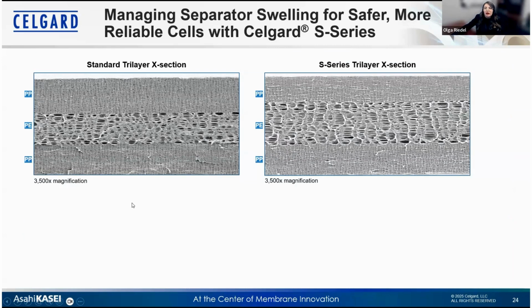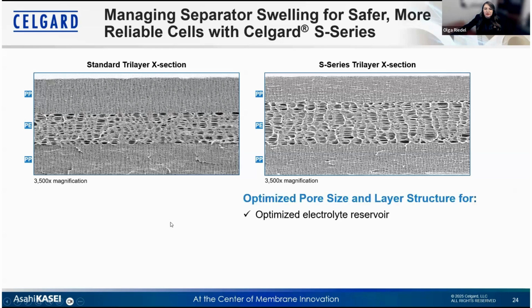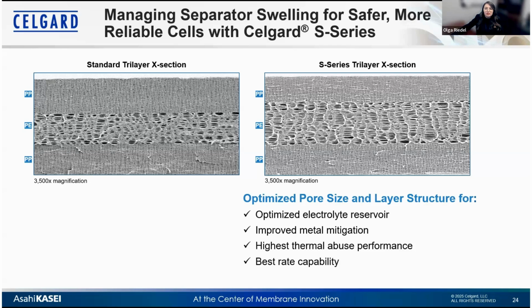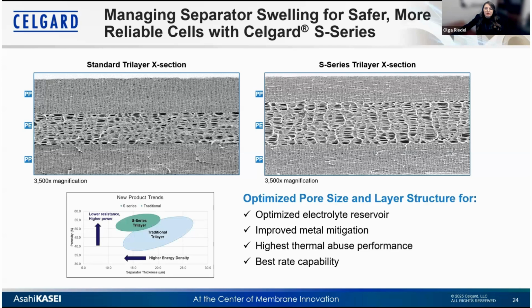At Celgard, we developed our so-called S-series trilayer that differentiates from the traditional trilayer by an improved layer structure and also improved pore size. This helps to create an optimized electrolyte reservoir in the middle PE layer, but also helps with thermal abuse performance due to faster shutdown of our optimized layer structure. Additionally, the low Gurley and the higher porosity help to improve the power performance and therefore enable the best rate capabilities among all of our trilayers.